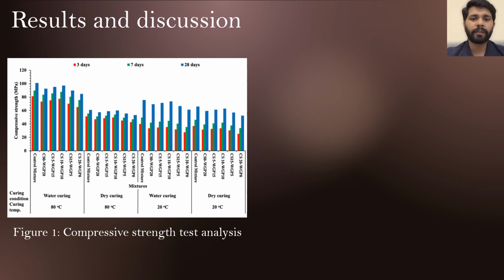However, with 10% incorporation of Cenosphere and waste glass powder, the compressive strength has slightly increased. The gentle increase in compressive strength at this replacement can be credited to highest packing density and lowest void ratio in this design mix. And the second reason may be attributed to the amorphous silica present in Cenosphere that reacted with calcium hydroxide in cement and promoted hydration product which ultimately increased the compressive strength.